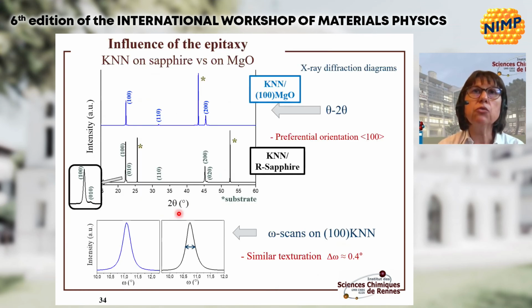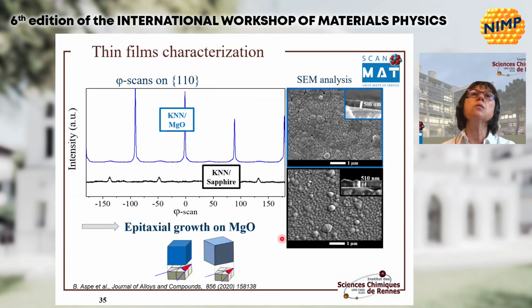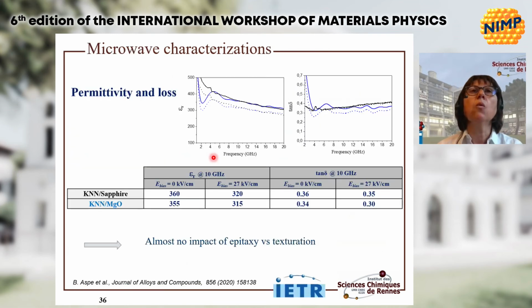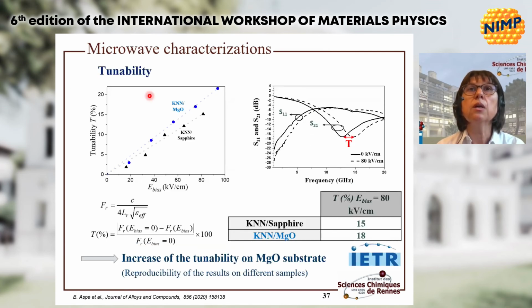Then, what about the possibility to change the structural quality? Thin films have also been deposited for comparison on 100 MgO substrate. We can see that similar texturation and rocking curves have been measured on both substrates, sapphire and magnesium oxide, but on magnesium oxide, a beautiful epitaxy has been obtained in comparison with sapphire. And in fact, what is the impact? There is almost no impact of epitaxy concerning permittivity and loss. But if we have a look at the tunability, we can see here that the tunability is higher, by 3%, measured in the same conditions on magnesium oxide.